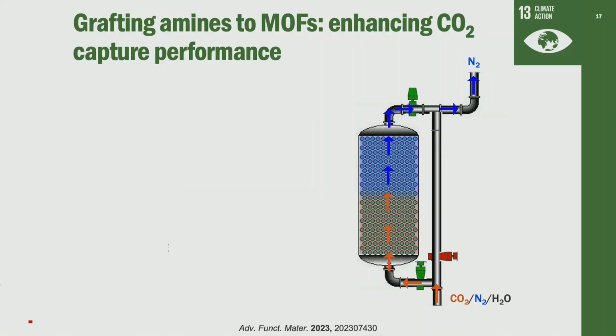We've looked at only CO2 and only nitrogen to see how much it absorbs, how much it takes up. Here we begin to look at these materials in gas mixtures. So here you can see our gas mixture has carbon dioxide, nitrogen, with and without water. What we do, we simply stream the gas mixture through the materials.